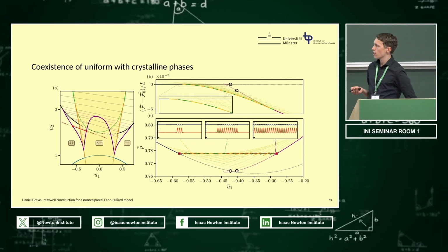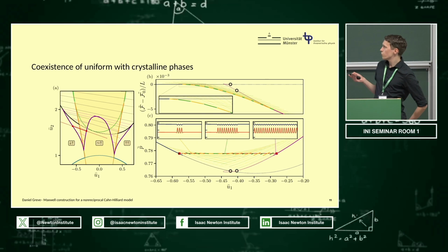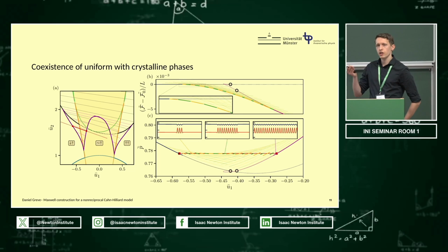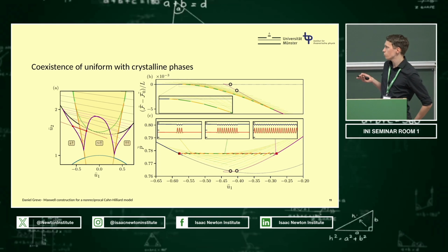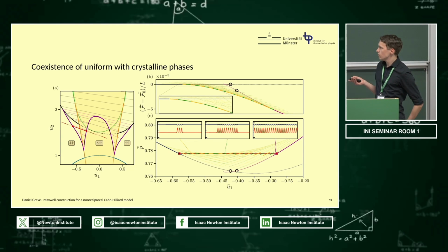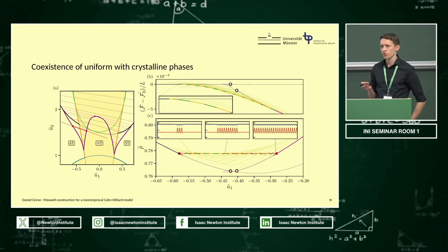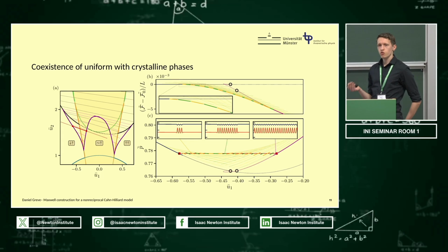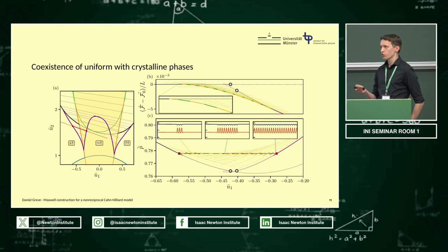Okay, D is a binodal for crystallization. So you walk along this binodal line. And what you can then see is, if you plot your energy and all the localized states, you get snaking, like in a phase field crystal model, so you get these localized states. And if you order them by the extrema of the energy and then arrange them in the pressure plane, they perfectly align with the Maxwell plane, with the Maxwell line. So the whole message here is, despite this crystalline state only occurring because of your non-reciprocity, this Maxwell line fully explains the crystalline states that you see here.